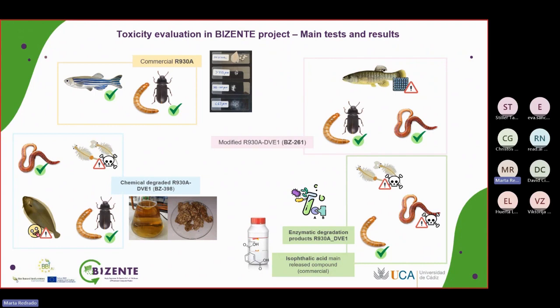When we tested the chemically degraded resin, we could also see good results for the worm and the Tenebrio molitor, and also some stress in the fish. It has to be noted, although it's still not conclusive, that the preliminary results show that in the artemias, when the concentration of the chemically modified resin is above 0.85 grams per liter, there was a mortality in 50% of the population, okay?